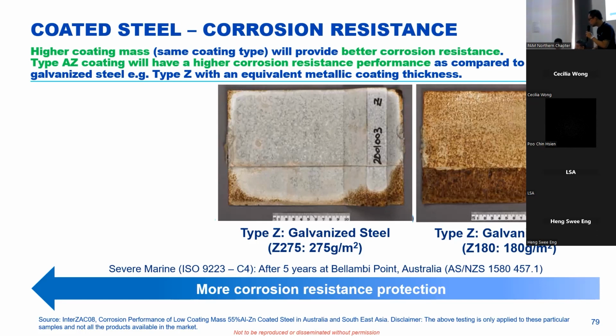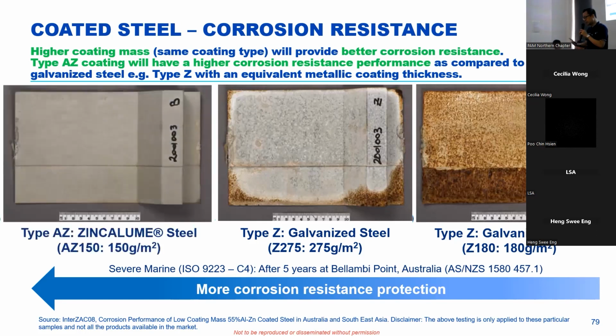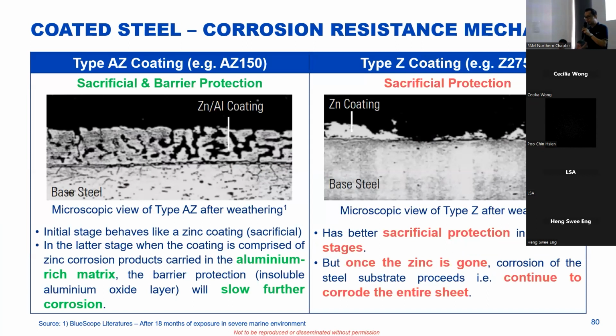What if I change to use the type AZ technology, the aluminum zinc coating, for example? This one is using the AZ class. Even though the coating weight is much lower than the Z sample, it's still able to outperform the GI sample, which is actually much thicker. The reason it's so different is that the type AZ technology is more superior than the type Z. That's why from this image you cannot see anything happening on the sample. And this is to showcase the mechanisms that the coating uses to slow down the rate of corrosion.